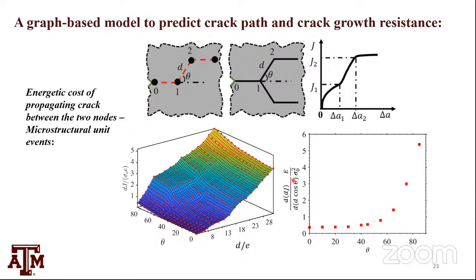Then I plot this slope. Change in dj over delta a2 minus delta a1, that's d cos theta, which is nothing but delta a2 minus delta a1, normalized by sigma naught squared over E. And I get a function of theta. This parameter doesn't depend on d, since d already enters in the normalization. This normalized quantity is simply a single function of theta. So this problem is slightly simpler.